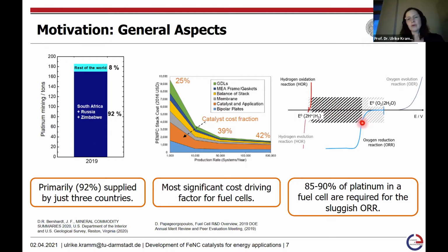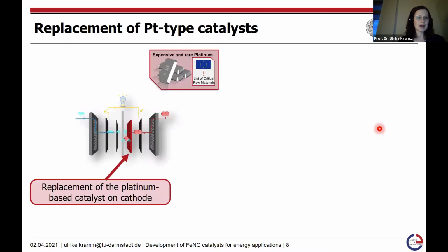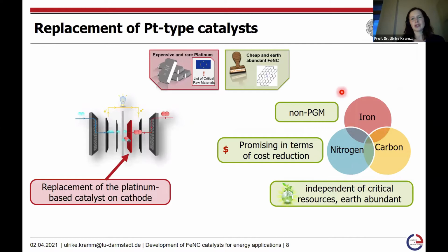then you can see that the overpotential loss on the oxygen reduction reaction side is much larger. Based on that, most of the platinum is required for the oxygen reduction reaction. That means if we are able to replace platinum on our cathodic side, then we can enable a drastic reduction of the overall costs of a fuel cell system. And this, of course, would be nice, as it would enable the utilization in a broad range. So just to sum up, the aim is to replace the platinum-based catalyst materials on the cathodic side by our cheap and earth-abundant non-precious catalyst materials.